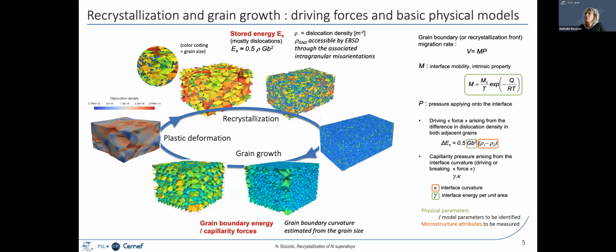Then the grains would grow. If you stop deforming, then the grains will keep growing until the stored energy is fully consumed. And then the microstructure continues to evolve to reduce the amount of grain boundaries in the microstructure. So there, the driving force is no longer the consumption of stored energy, but the minimization or the decrease of the interfacial energy. This regime here, after the consumption of the stored energy, is referred to as the grain growth stage. For describing these phenomena, we have a number of physical laws and quantities to handle.